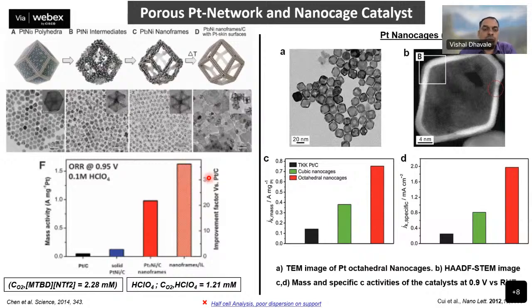So if you look into these two recent articles, which triggered the research area or development in such kind of nanoframe structure. One was the Science paper in 2014, where the ignition started for such kind of nanoframe structures. So if you see over here, these nanoframe structures started with the Pt-nickel, and eventually you can leach out the nickel from the core as well as from the walls, and you will end up with the open architecture structure.